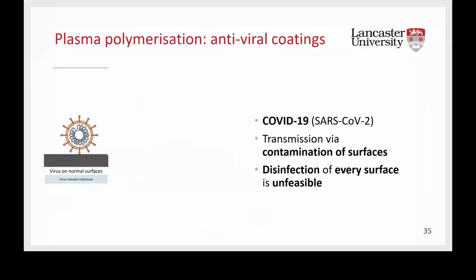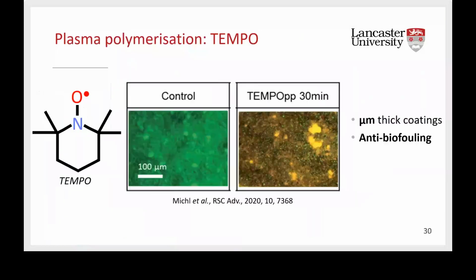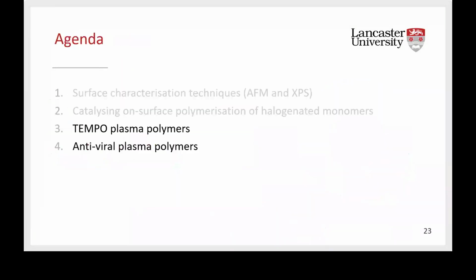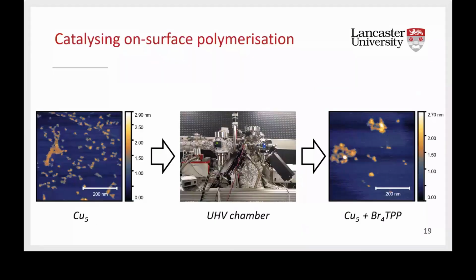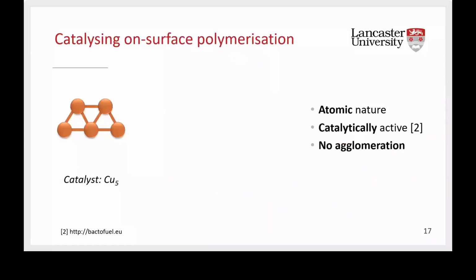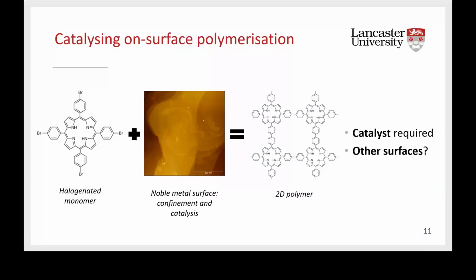Okay, so these two-dimensional polymers can be used for catalysis because they can form these very nice ordered structures. Let me see if I can show you. They can form a perfect structure like this one that can selectively host molecules and thus can be used for catalyzing specific chemical reactions. Also, in particular, porphyrin can host metal atoms in the middle that are catalytically active. And in our research group, we are actually using some of these metal porphyrins that can catalyze reactions such as the hydrogen evolution reaction, so production of hydrogen.